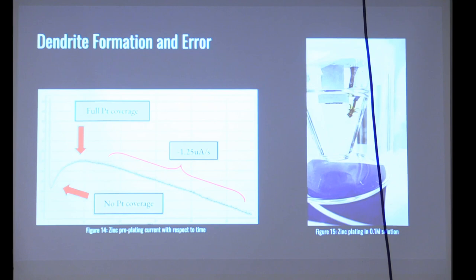This plot shows the initial plating of zinc prior to measurements. You need to plate zinc onto the electrode to ensure it is not depleted when taking reaction measurements. There is an initial spike in current when there is no zinc on the platinum electrode, which slowly reduces as zinc covers the electrode. The downward slope on the graph indicates decreasing current over time, suggesting that as zinc forms dendrites it creates greater reaction area, influencing the performance and measurements. This shows that dendrite formation is something we need to consider moving forward — it is probably a primary concern when actually designing the reaction cell.